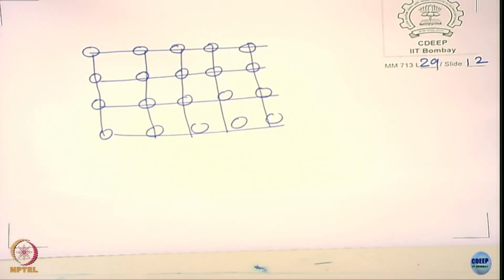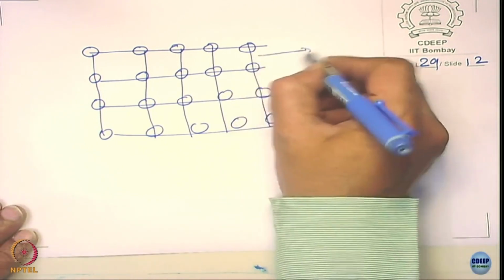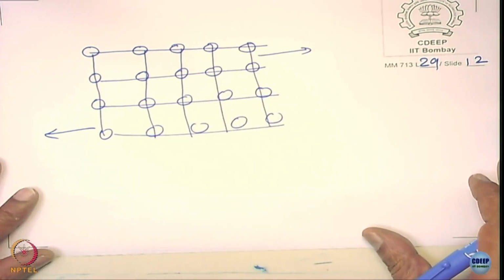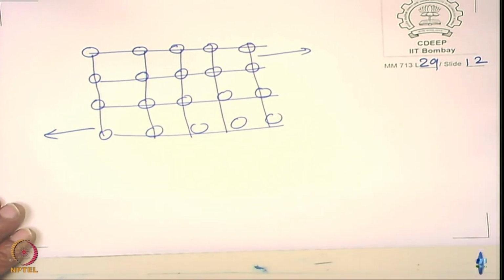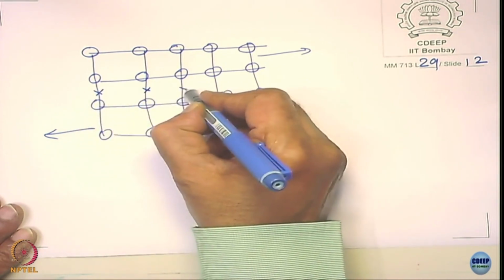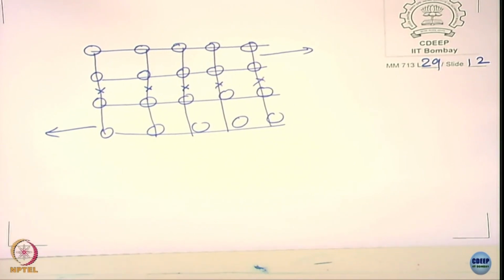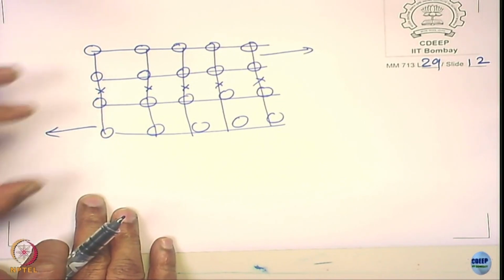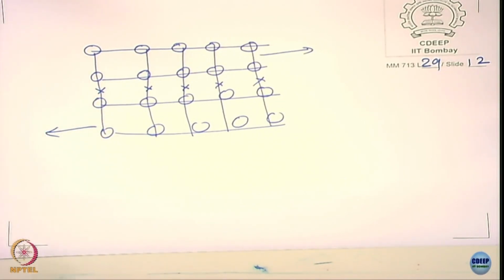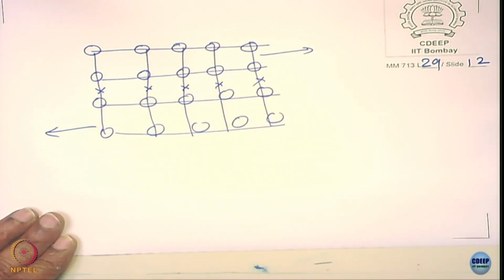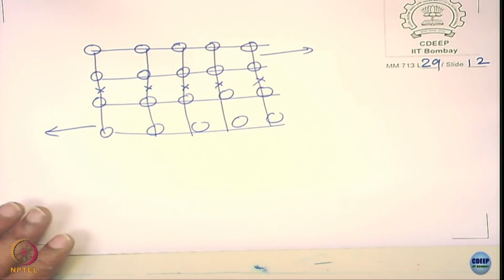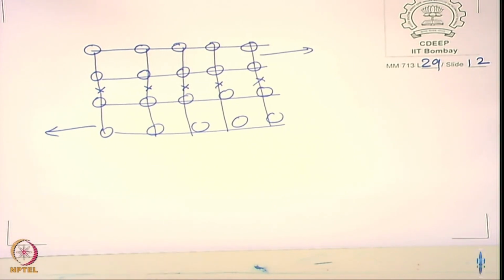In the lattice that I have, when you apply force, atoms start moving when you have dislocations. If you have no dislocations, of course it is difficult for them to move. Now when you pull it, assume that I use a scissor and cut this bond, this bond, this bond. If I cut these bonds, what happens? This piece becomes separate from that piece, which means the atoms are intact and their positions are not changed, because the bonds are weakened. So cleavage fracture essentially means the bonds between the atoms are broken well before the atoms could displace from their positions.